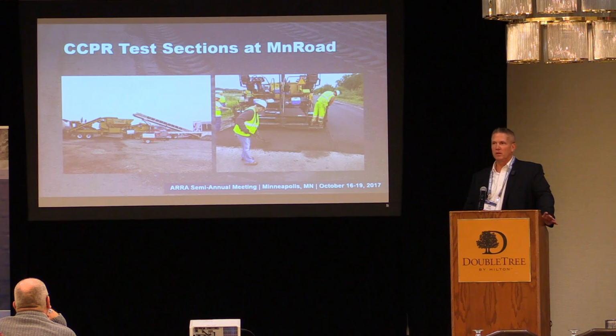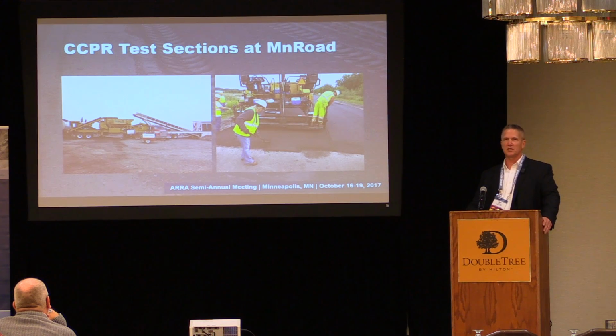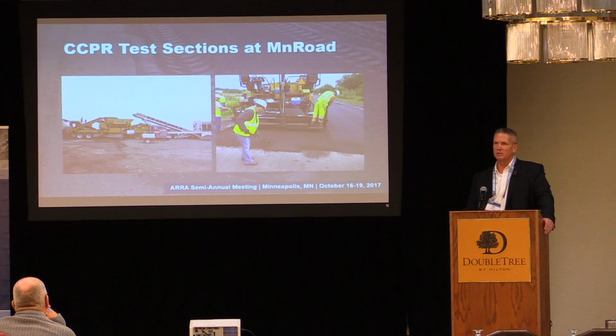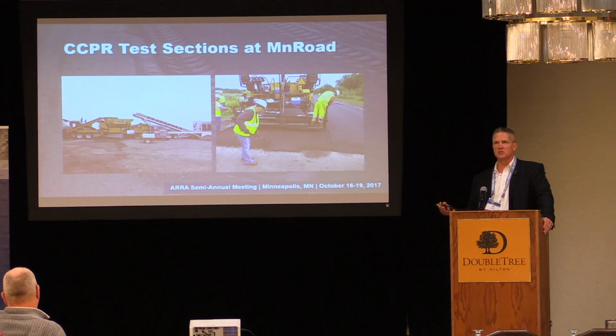In addition, what you'll see out there are some sections that were placed this year, somewhat because of this research. Foamed asphalt and engineered emulsion were selected for additional work on the low volume loop. Two test sections were placed using cold central plant recycling, where the material was manufactured off-site and brought out to MnRoad and then laid through a paver. There's 2 sections of foamed asphalt, and there's 2 sections of engineered emulsion.